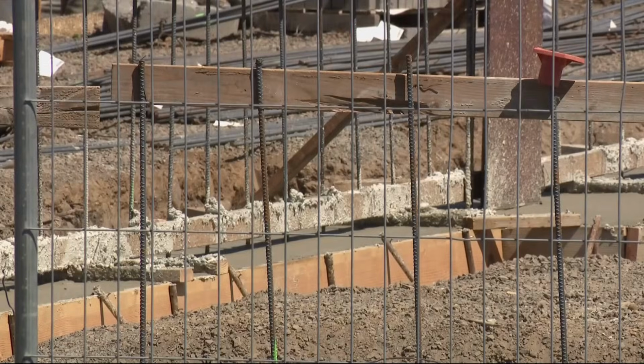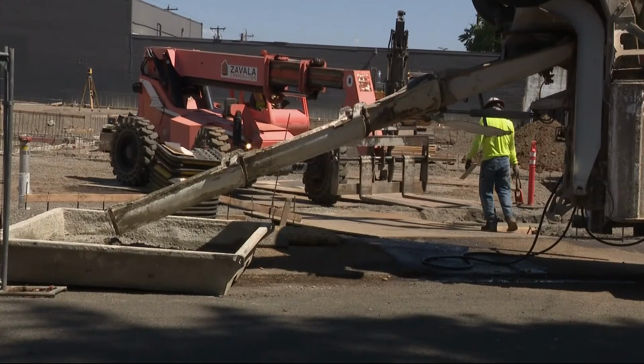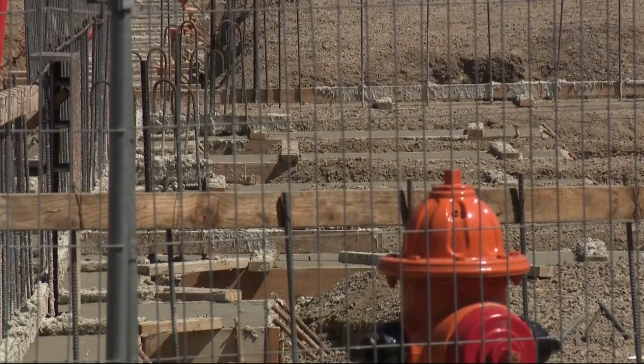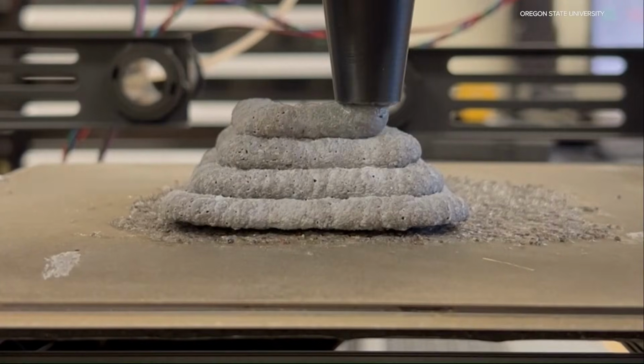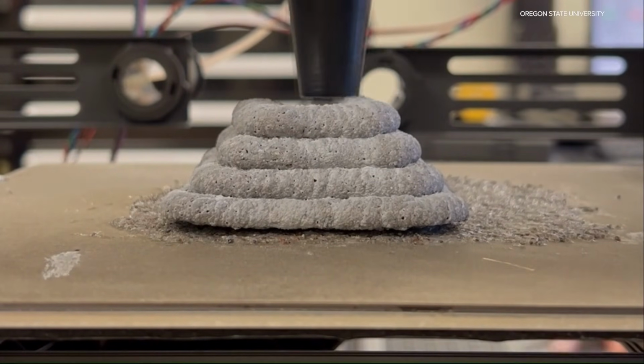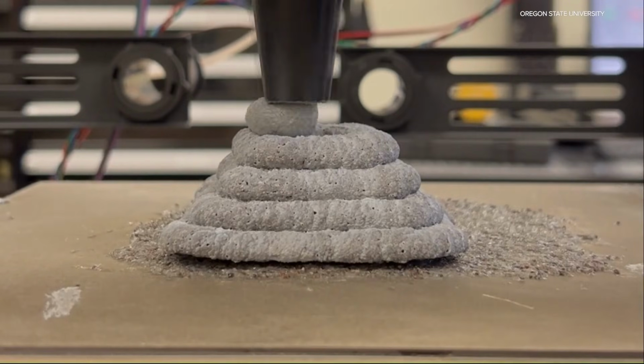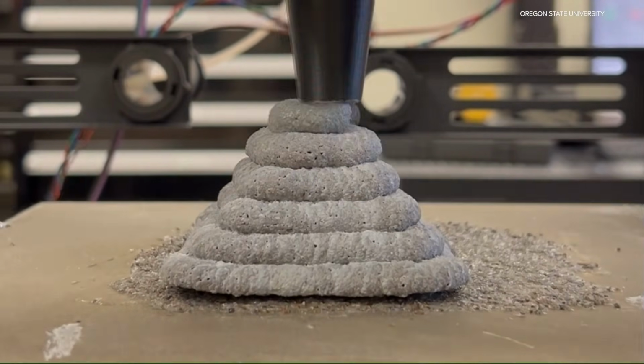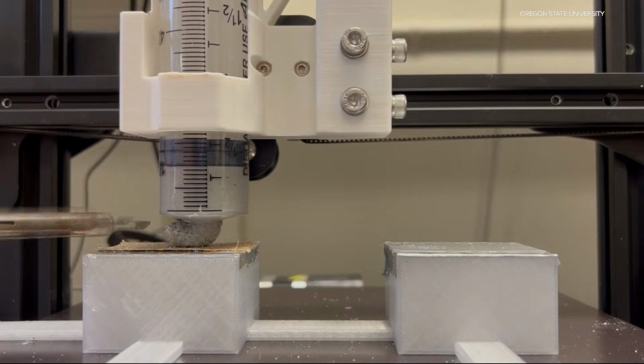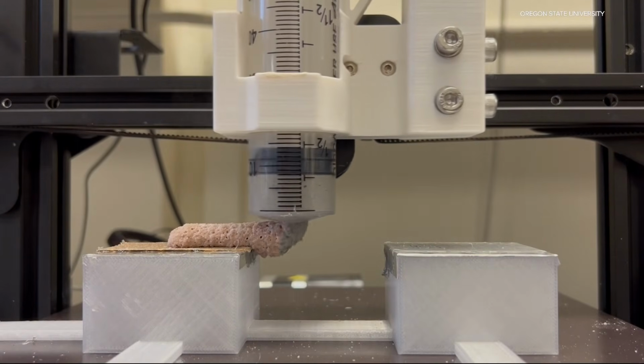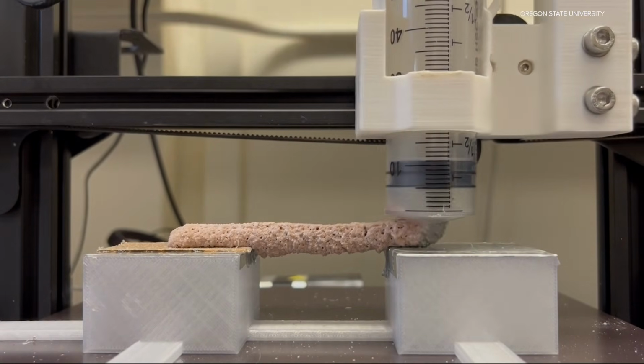Current 3D printed concrete homes often require days of waiting between layers while the concrete cures. For every layer that gets printed, they have to wait a few days for those layers to cure before they can come back and begin to print more layers. With our material, essentially it cures immediately, so we can print the entire house that same day. The material also gains strength quickly, reaching structural requirements in a fraction of the time.